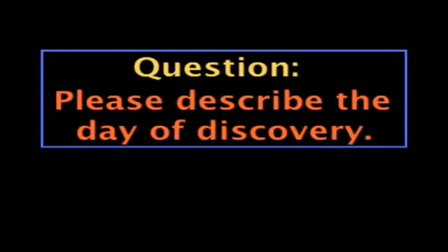It was in the morning. I was alone in the electron microscope room looking at a new material that I had just created, composed of aluminum and manganese. Right there, in the beginning of the morning, I looked at the material and it looked very strange to me. And I took an electron diffraction from that area that looked strange. And lo and behold, I see a diffraction pattern that has 5-fold rotational symmetry.